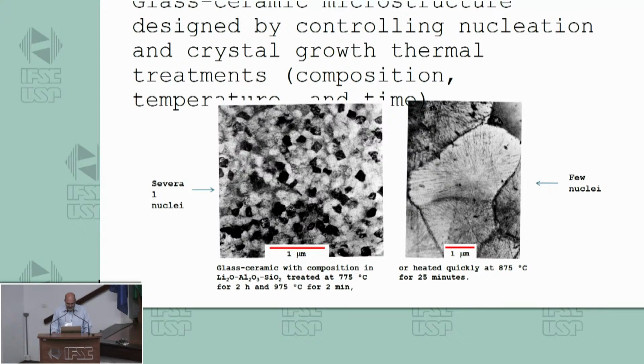Then, glass ceramic microstructure can be designed by controlling nucleation and crystal growth. For example, here on the left, there are many nuclei, so we spend more time in the nucleation step to achieve higher nucleation density, and then we heat again for crystal growth at a higher temperature, and then we crystallize all the glass, obtaining very small crystals because they stop growing when they hit each other. Okay?